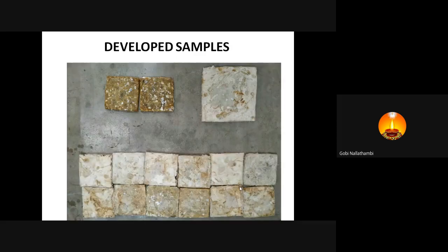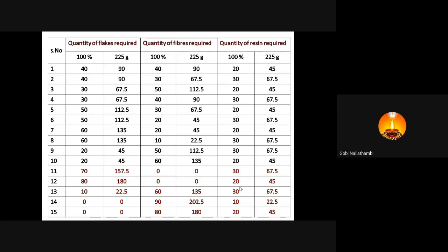If you see the proportion, samples 11 and 12 do not have the fibers. They have only the flakes. So the reinforcement material is only flakes. Because of the absence of fiber, there is no intermingling or interlacement. We can say there is no interaction of fibers and flakes. When the fibers and flakes are interacted or mixed, and integrated in the composite structure, it gives higher performance with respect to the tensile strength.